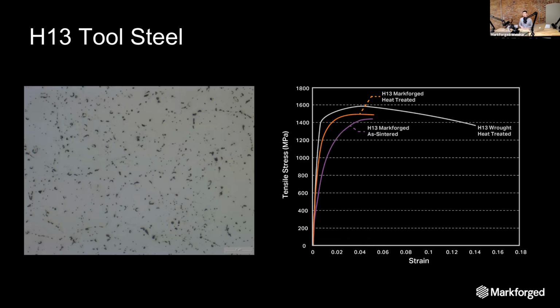As a byproduct of a MIM system, the parts generally don't elongate as well. So if you're familiar with our 17-4 data sheet, you'll see something similar, where a normal wrought 17-4 extends about 1 to 1.5% by unitless numbers before breaking, and ours goes about 0.5%. You'll see a pretty similar thing with H13, where it is a little more malleable. It can extend a little further in a wrought scenario than in a heat treated, printed scenario. Overall, that's not a massive issue when it comes to usage.